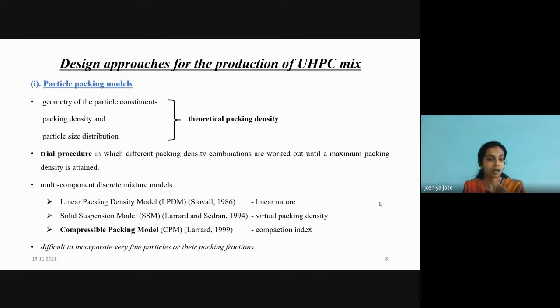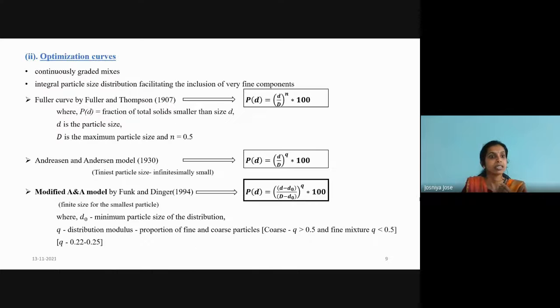But all of these models deal with the packing fraction of individual material components, that is, it can be sand or cement. They do not consider an integral particle size distribution. So the further development is using the optimization curves. They provide an integral particle size distribution, and this facilitates the inclusion of very fine components in the matrix. So they are continuously graded mixes which assume all possible material classes to be present in the matrix. This dates back to 1907, where the Fuller curve was developed by Fuller and Thomson. They found that continuously graded mixes improve the quality of the developed material.